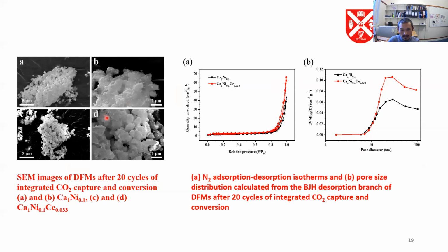So we did some further analysis. We assume that for the first one, without cerium oxide, the pores become blocked after a few cycles. From here, we can see this from the porosity and also the SEM. I think for the first one you can see it becomes quite solid without cerium oxide loading.